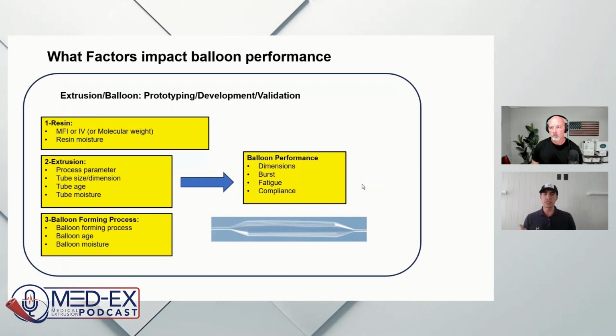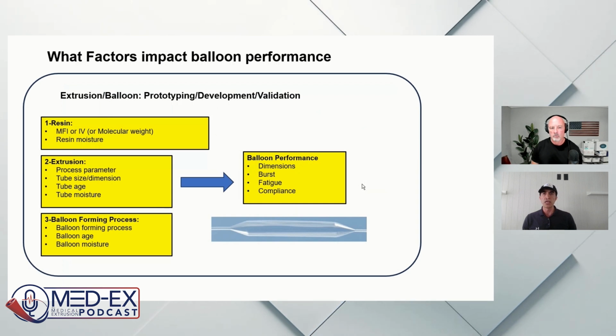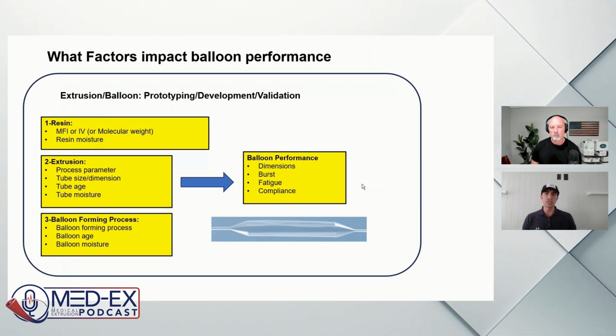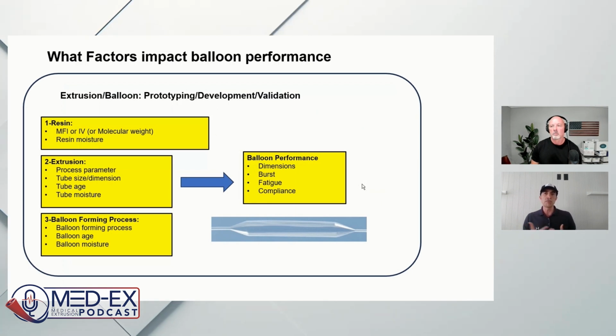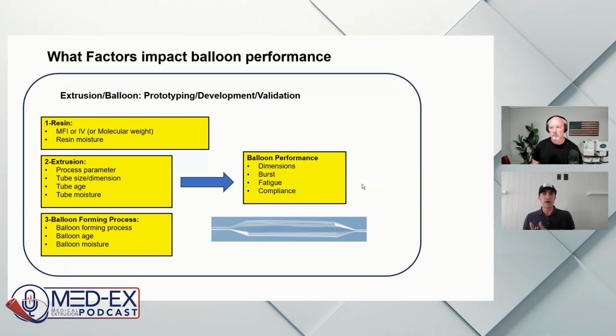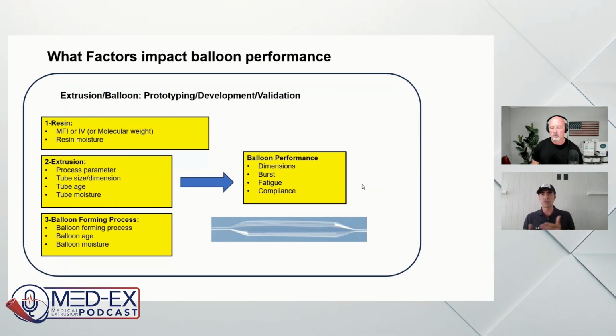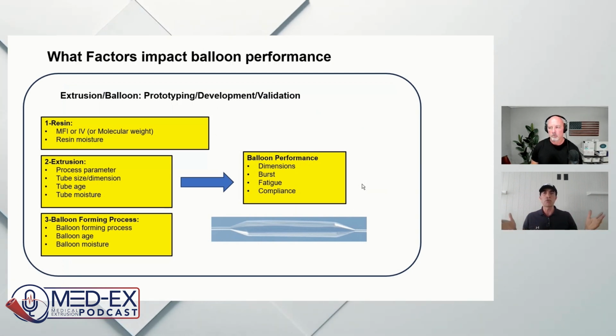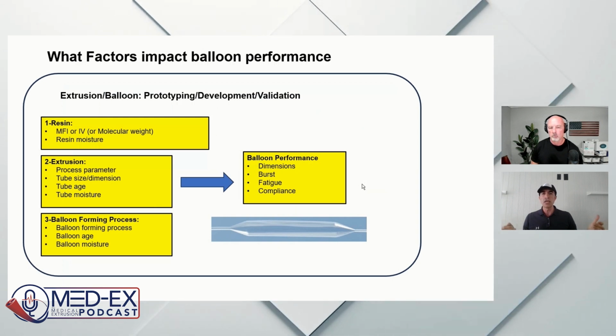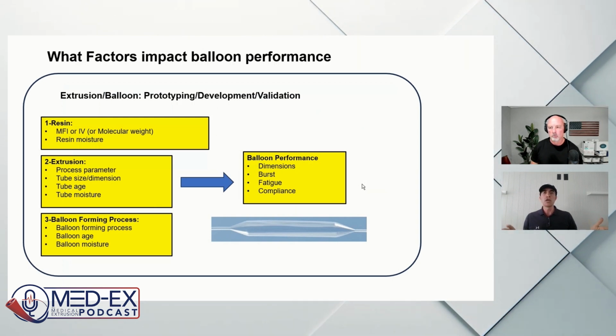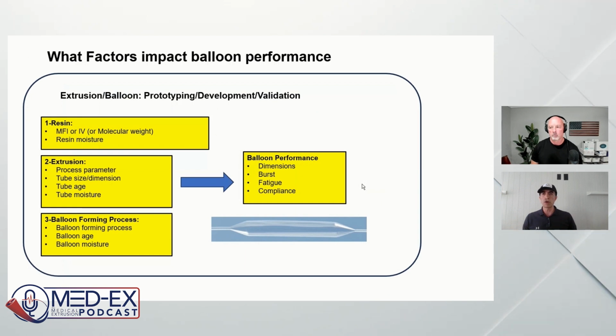If we start from the resin, of course, resin is a very important part of the process. You use that to extrude your tube. And of course, the melt flow index or intrinsic viscosity of the resin, which represents the molecular weight of the resin, is very important. The higher the molecular weight, the lower the MFI, or the higher the intrinsic viscosity, depending on whether you're using nylon or PEBAX. It would have an impact, right? A higher molecular weight means that you have more entanglement density in the melt, and could potentially give you a higher strength for the final part.